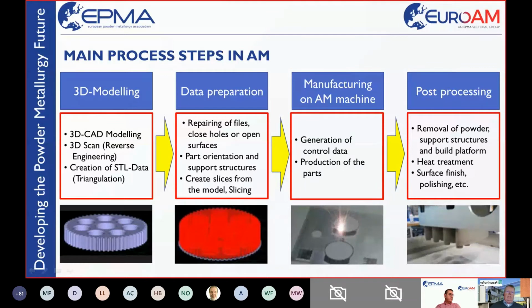So STL data is triangulated surface data. This data of the model is then prepared, so pre-processing for the printing step itself. Holes can be repaired, the surfaces can be closed, the part orientation is defined, so the positioning in the build chamber is defined, and then this model data is sliced, so cut into slices, so it can be printed layer by layer for most processes.